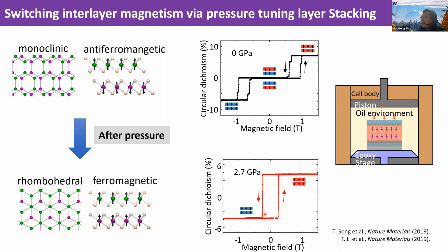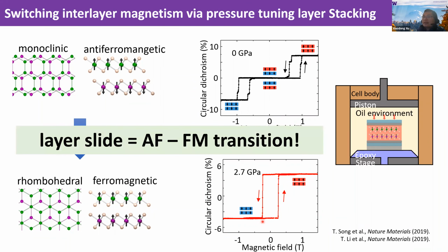You will see a very pronounced hysteresis loop near zero field. So this shows the crystal now becomes ferromagnetic. This example shows that by applying hydrostatic pressure, we introduce this layer slide, and then we have an antiferromagnet to ferromagnet transition.